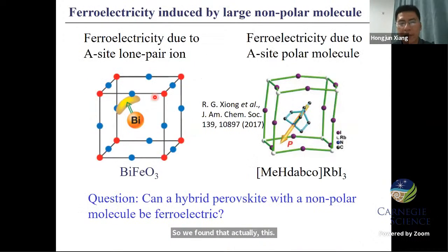People usually consider the lone pair ion as an A-site ion giving rise to ferroelectricity, but we found that even when the lone pair ion is located at the B site, this can also give rise to ferroelectricity. This can be seen from a simple model.